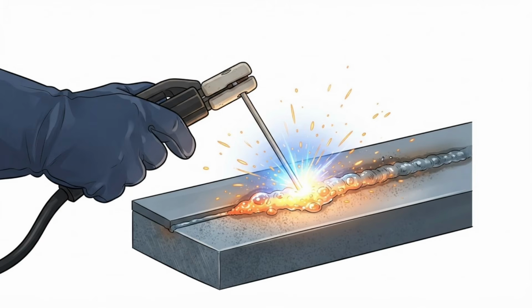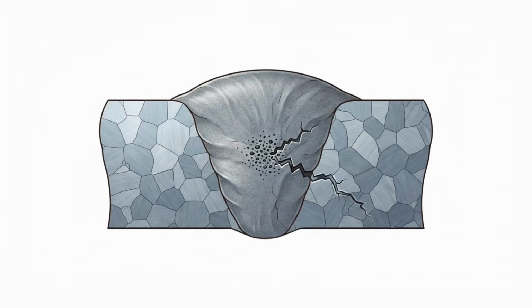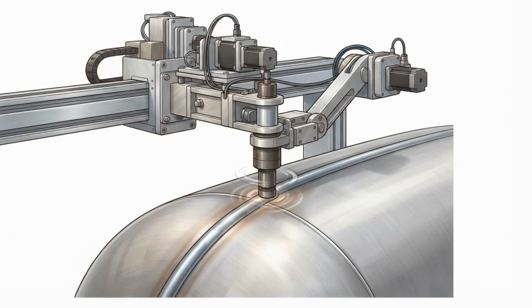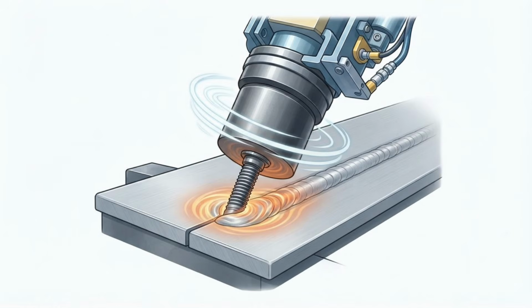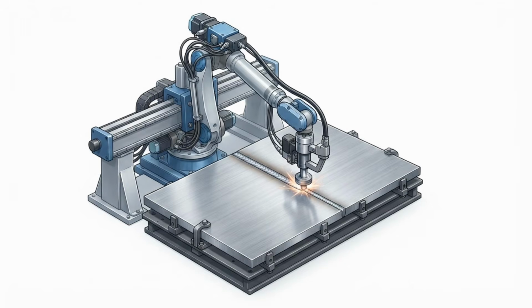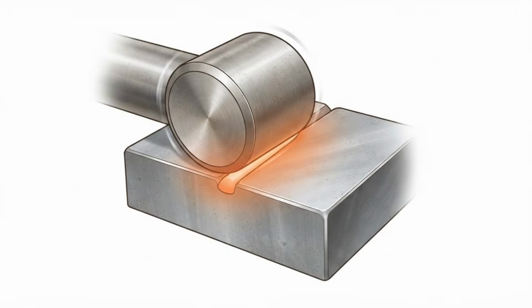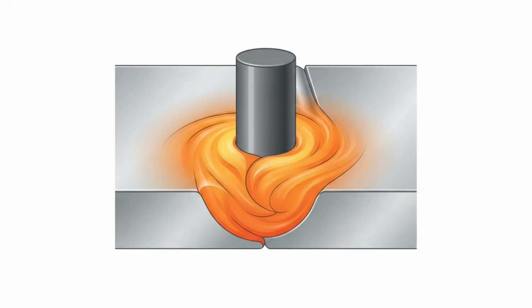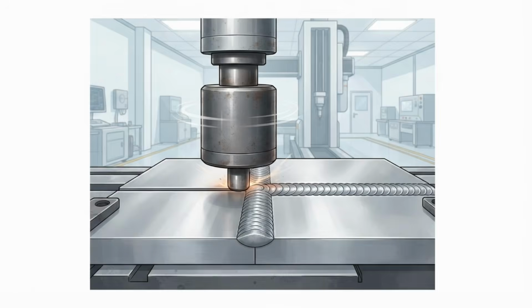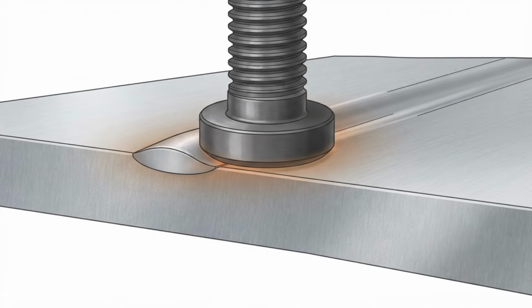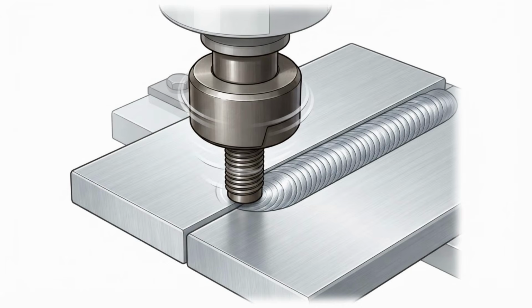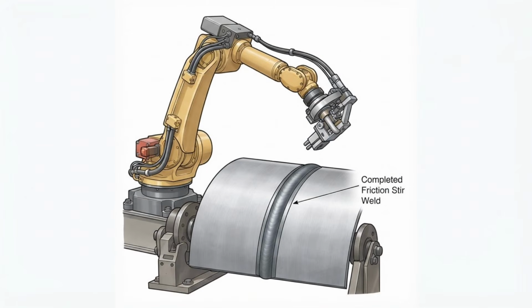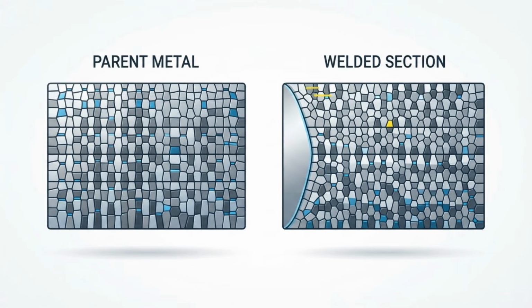Joining these massive metal sections together poses a unique challenge. Traditional arc welding melts the metal, which destroys the carefully engineered strength of the alloy and introduces microscopic flaws. Instead, rocket engineers utilize a process called friction stir welding. In this technique, a rapidly spinning, heavy-duty cylindrical pin is forced into the seam between two metal panels. The intense friction generates massive heat, softening the metal into a plastic, putty-like state without actually melting it. As the spinning tool moves along the joint, it mechanically mixes and forces the softened metal from both panels together, forging a solid-state weld that is nearly as strong as the parent material.